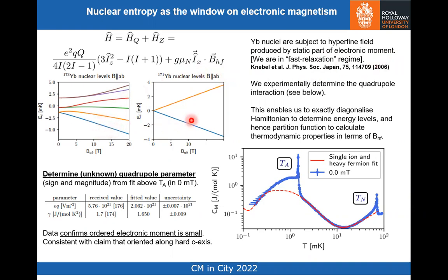These are the energy levels for the 2 spin species, which were obtained for us by diagonalizing the Hamiltonian by Andrew Ho. So for this data here in zero magnetic field, effectively, we can neglect this term here because the local moment is so small, and so we can fit the data above this transition to the heavy fermion contribution. That's the gamma of the heavy fermion system, which agrees with the accepted value, and the magnitude of the quadrupole interaction, where we obtain a number that was significantly smaller than the accepted value. But on closer examination of the literature, there is no actual measurement of the quadrupole interaction under ambient conditions.